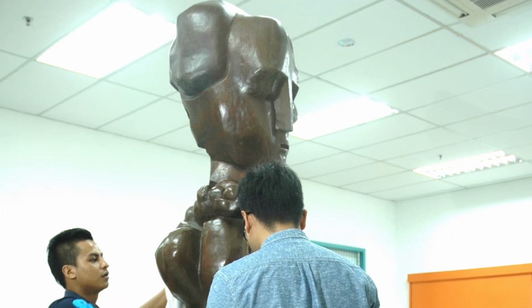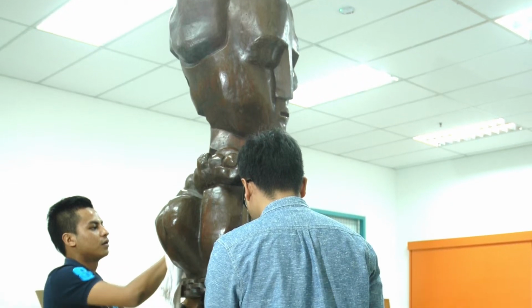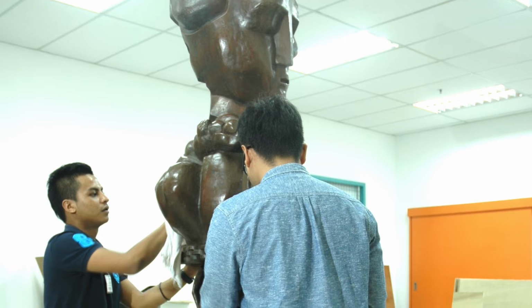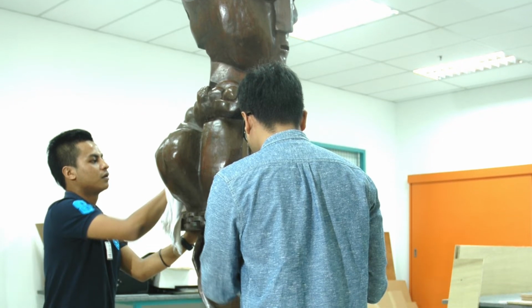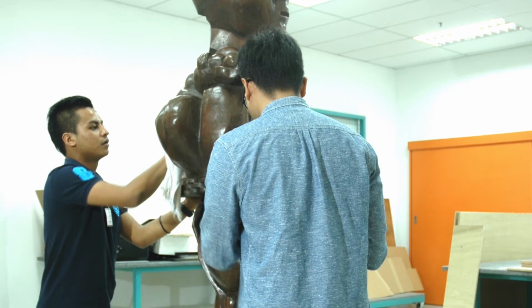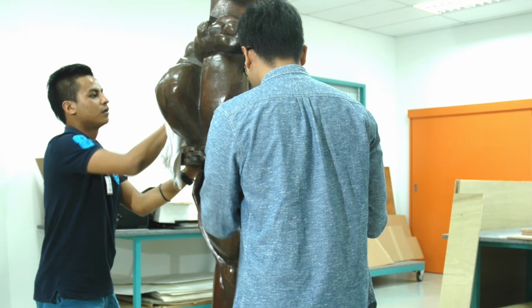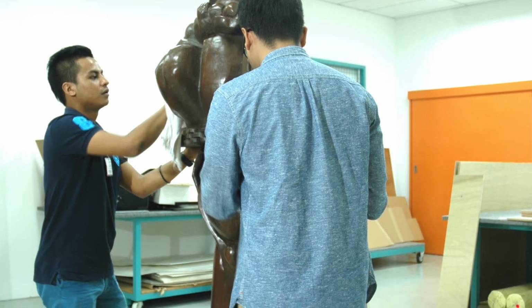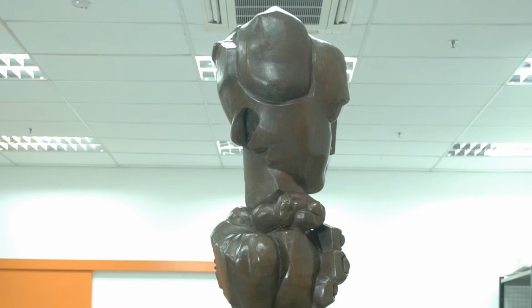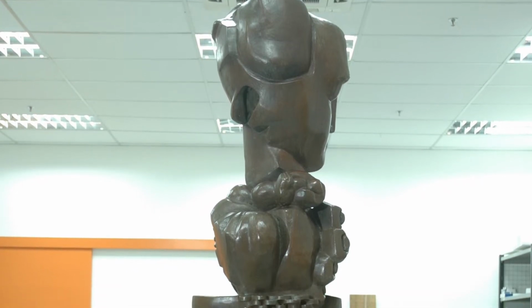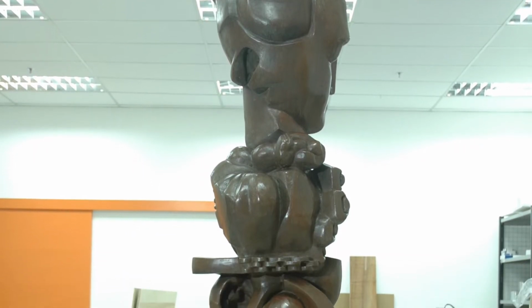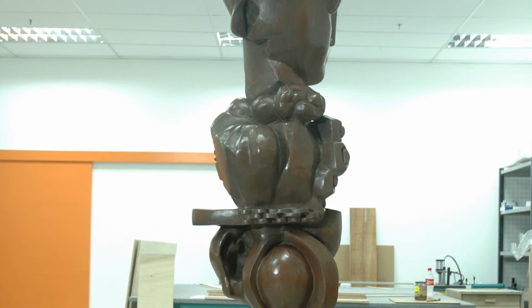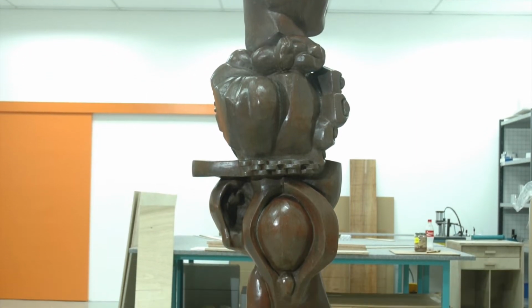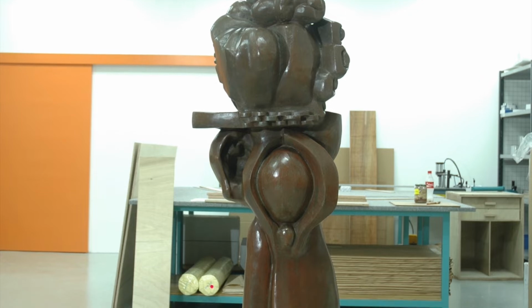The rate at which a bronze sculpture corrodes depends on its environment. In a tropical urban climate, this corrosion can occur and progress rapidly. This is mainly due to the high humidity and temperature, but also air pollutants. Both formic and acetic acids are major organic acids contributing to the acidity of rain. These acids readily attack and dissolve patinas, resulting in patchy and streaky surfaces.